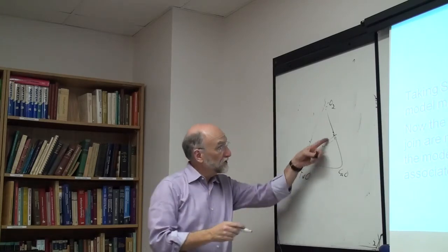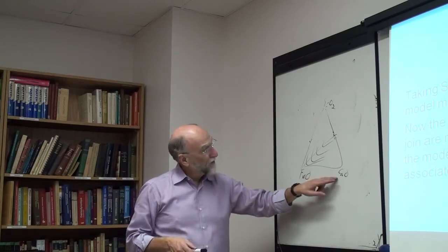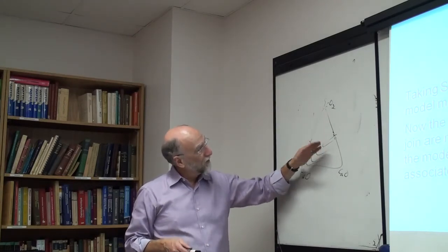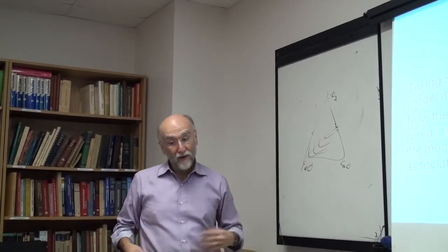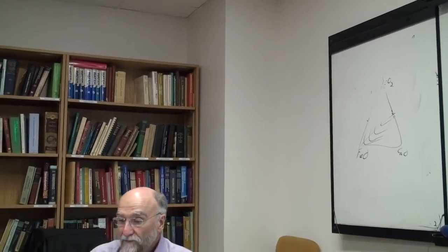And using Z as 2, we can reproduce that pretty well. But were the system a little bit more negative over here, and you actually had a miscibility gap, we would never get it. We couldn't reproduce it with Z equals 2. If you put in Bragg-Williams terms, you can. If you put in Z greater than 2, you can, but not with just Z equals 2 and no Bragg-Williams terms. I'll explain in a minute why that's the case.